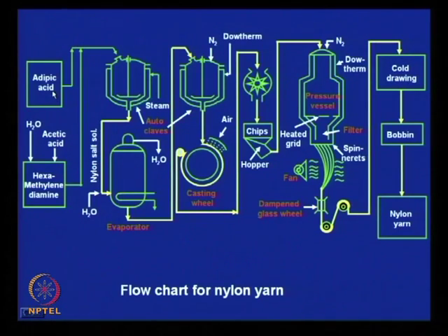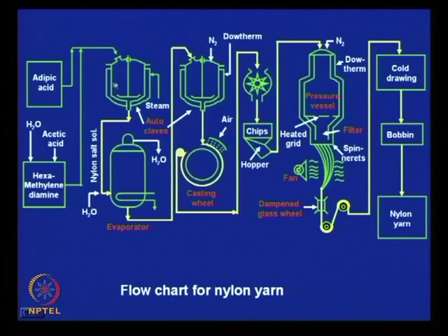mixture. But if you mix these two in solution phase, a salt will be formed in 1:1 molar ratio, and then that salt, since that is a solid, can be filtered and washed, and can be further proceeded to melt polymerization of that salt.